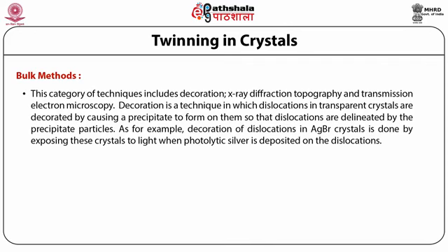For example, decoration of dislocations in silver bromide crystals is done by exposing these crystals to light, when photolytic silver is deposited on the dislocations.